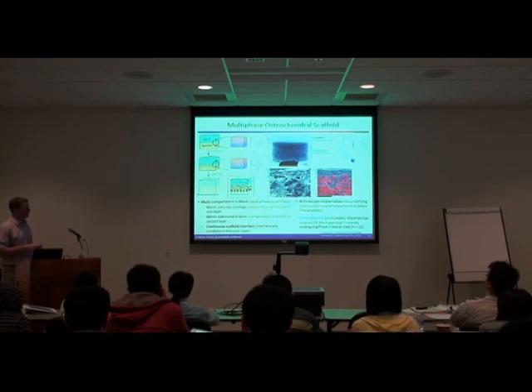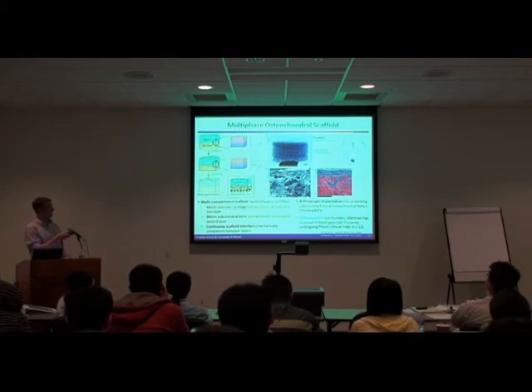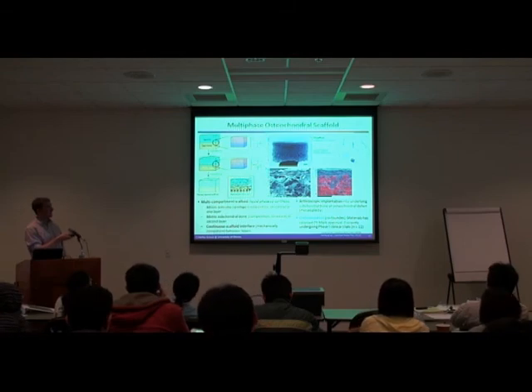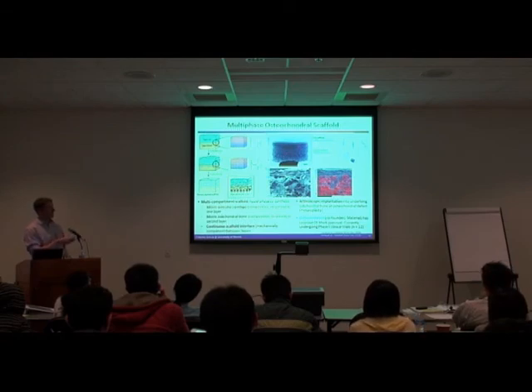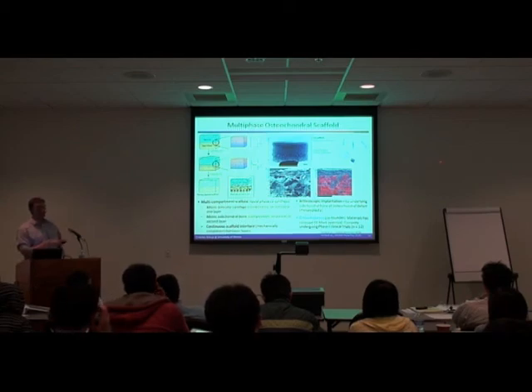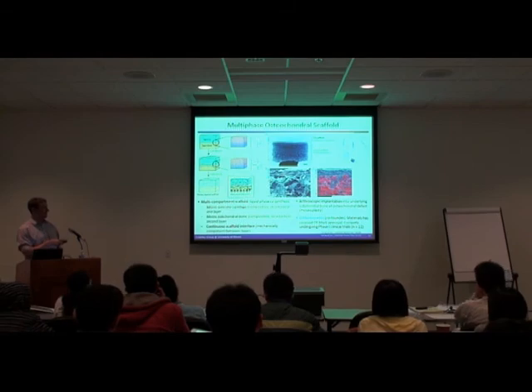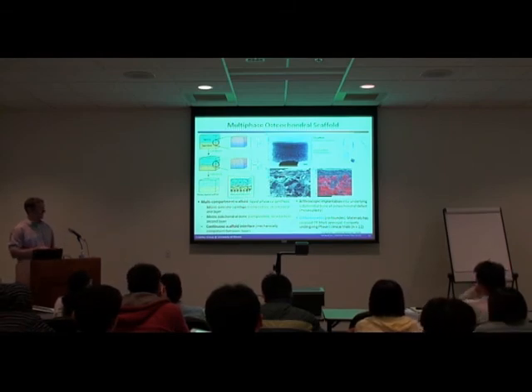So a few years later, we actually came up with a scaffold. This is a micro CT image of the side of our collagen scaffold that has a highly porous type 2 collagen GAG scaffold, cartilaginous compartment, and a mineralized type 1 collagen osseous compartment, and a continuous interface between the two. This is an SEM just looking at the interface where those collagen fibers go across, and this is an EDX image showing calcium phosphate concentration in the scaffold, in red superposed with the scaffold. So we have non-mineralized, highly mineralized, and this interface that takes place in between the two.